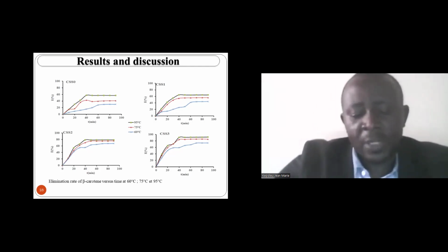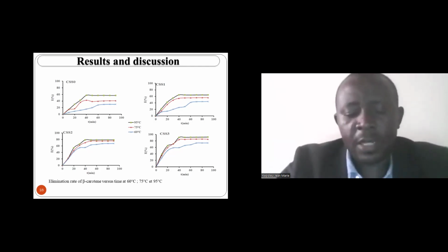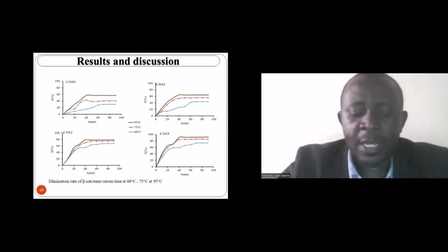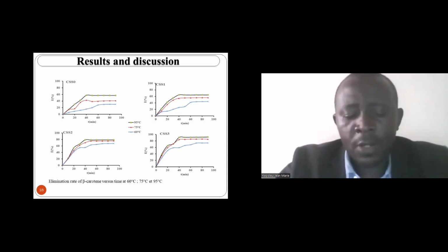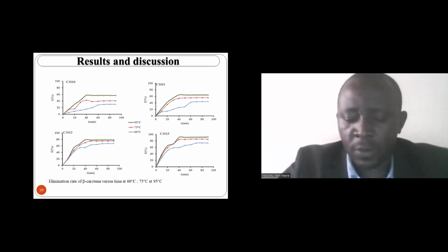So increasing temperature leads to less viscosity and more mobility of beta-carotene towards the surface of the adsorbents. Moreover, the rise in temperature is known to be a means of adsorption site activation, which obviously led to a rapid adsorption of pigments.